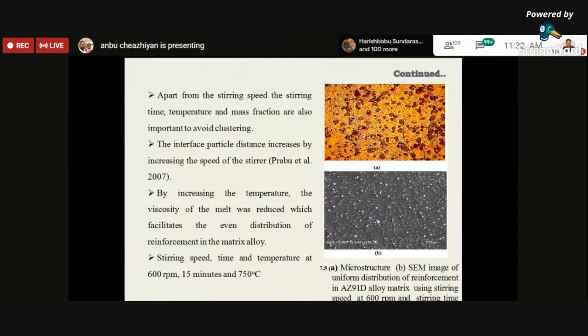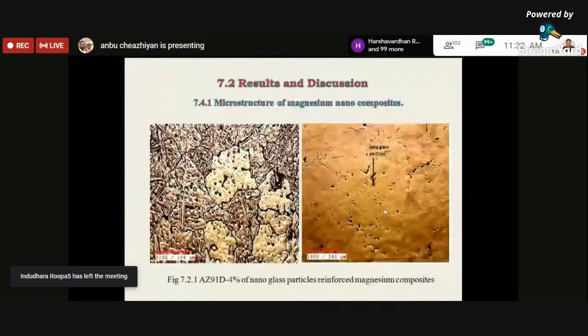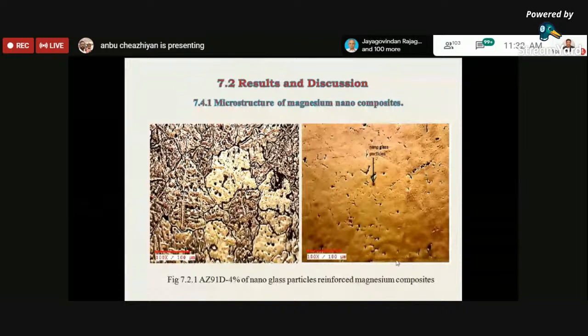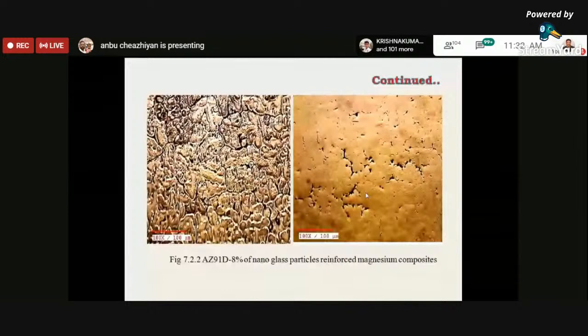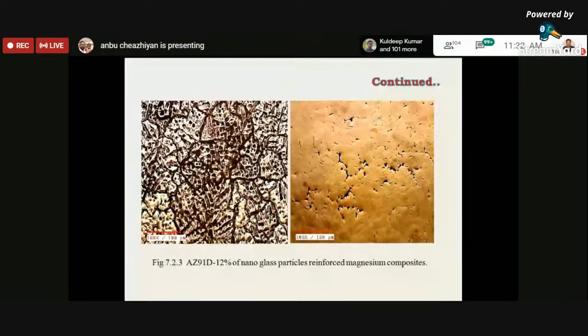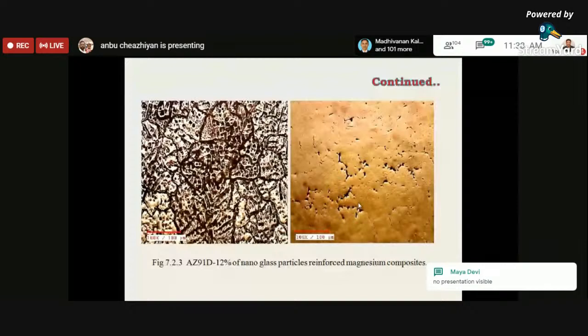These are the images of the glass nanoparticles, or sometimes hollow glass particles. These are the microstructures of the magnesium nanocomposites, and we still found some porosity on the surface of the as-cast samples. On the surface of the metal we saw some porosities, and through the cross section we saw the nanoparticles in it. This is the 4% nanoglass particle reinforced magnesium composite, and this is the 8% nanoglass particle reinforced. Picral is used as the etching agent, and this is the 12% nanoglass particles. With the increase in percentage, a larger amount of surface porosity is obtained in the as-cast samples.